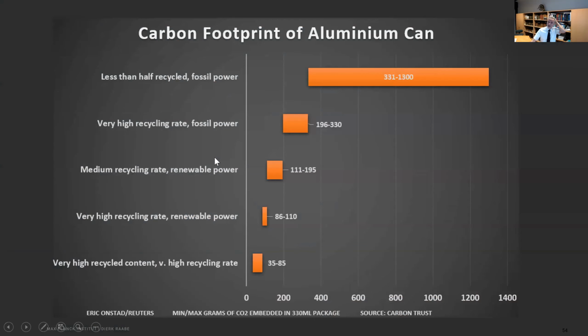But a very important point is, when you do an analysis of how you produce your aluminum, like I said in the very beginning, you must do it based on a very careful life cycle analysis. It's very often said that, for instance, all the primary synthesis of aluminum is very bad because you do it by electrolysis, but this is entirely incorrect, because when the electrolysis runs, for instance, totally on sustainable energy, it's perfectly fine. You just have to deal with the byproducts or with the electrodes, which are graphite and so on. So you must really look into the detail of a life cycle assessment, which aspect of something like an aluminum can production is really sustainable and which is not. The punchline, however, is of course that a high recycling content is always beneficial.